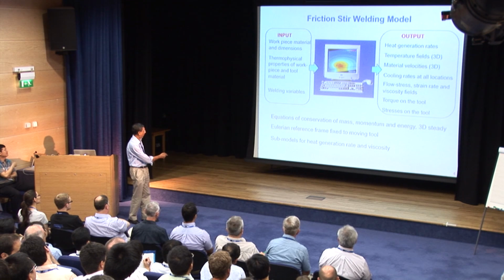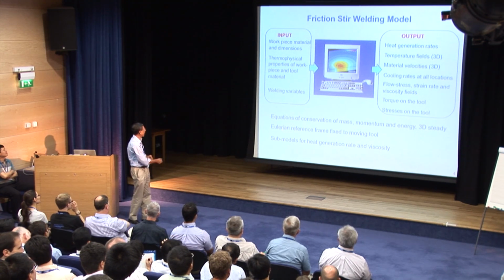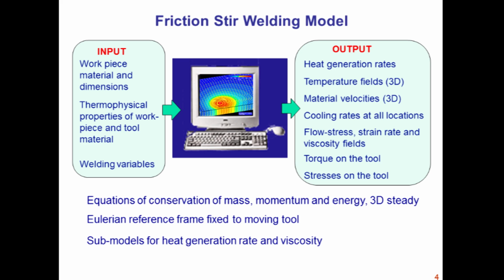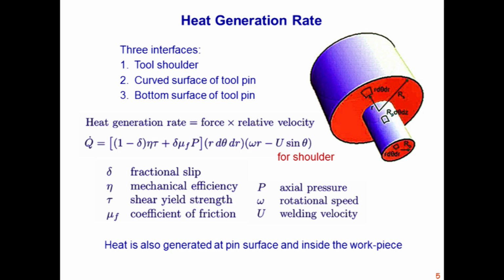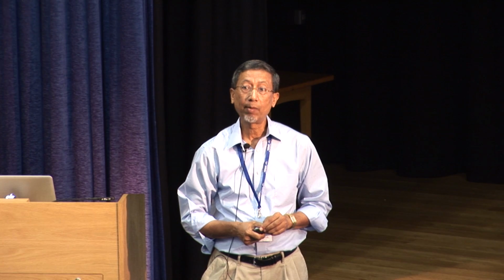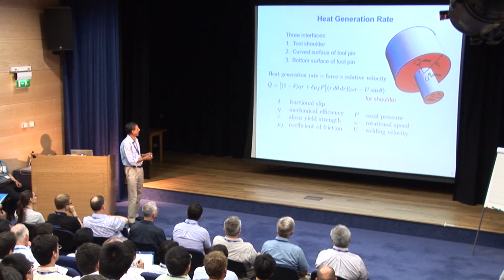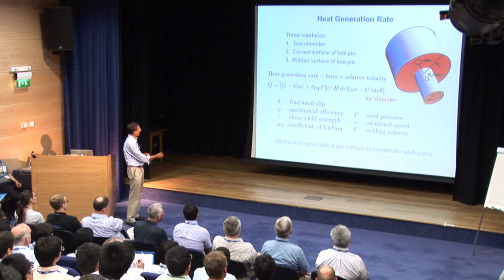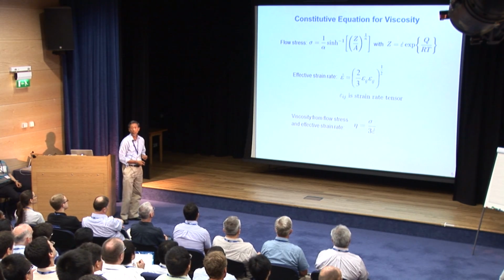All right. So to solve these equations, you also need submodels for heat generation rate and viscosity. Just a minute about that. The heat is generated primarily on the shoulder, but also on other surfaces, and to a much lesser extent in the entire volume of the friction stir welding. And we have to have a submodel to estimate heat generation rates spatially at all locations within the domain. And in addition, we also need a model for viscosity.